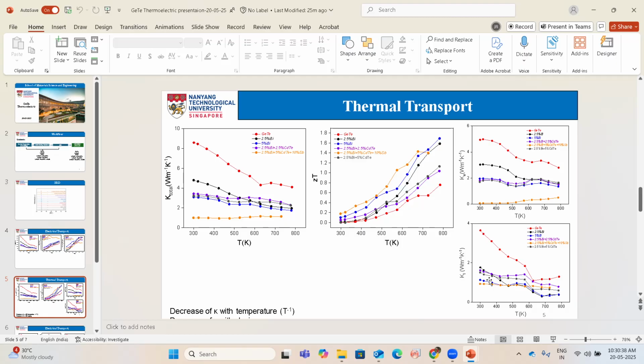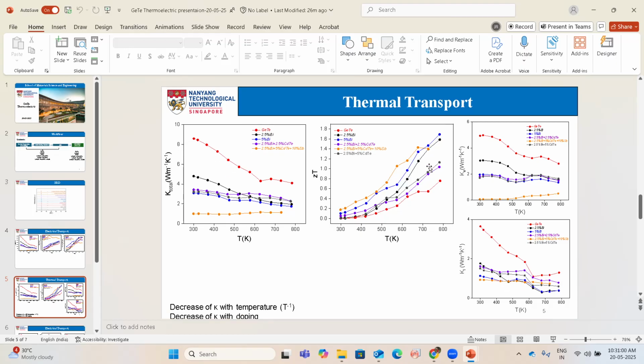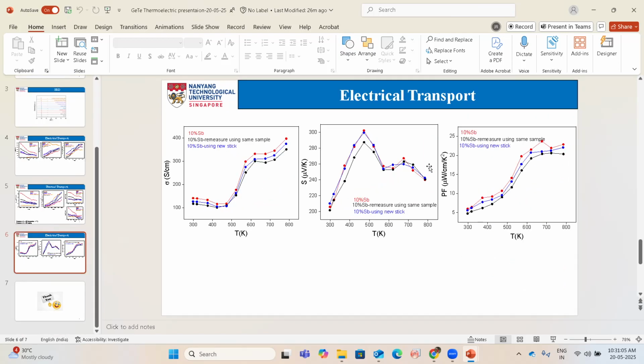I'm emphasizing that you should come up with your own hypothesis. Originally I remember you had a slide a year and a half ago on the choice of dopants and the ionic radii. But there are clearly three effects: one is dopant diffusion, one is ordering, and one is interface layers that is unique to this system. So you need to have a picture in mind of what each of these is doing with respect to the synthesis conditions. Then we can predict what we want to do with the new dopants.